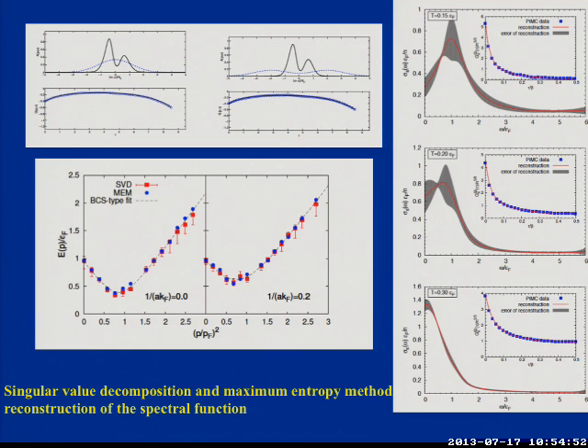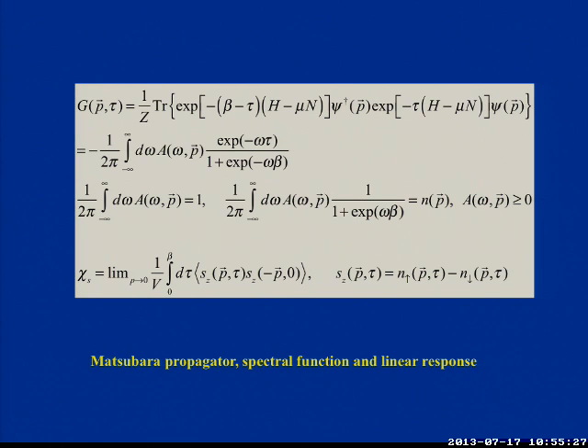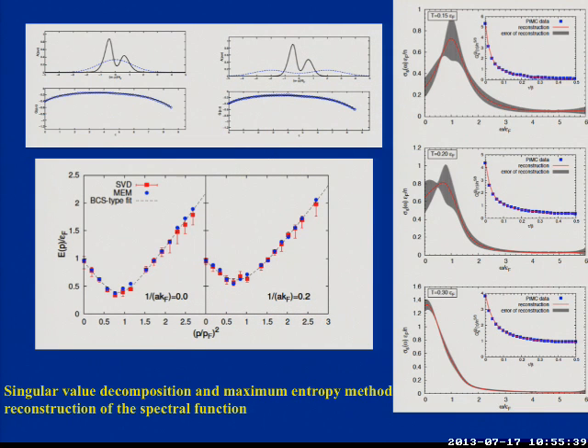Here to show you how well it works, you see here the green function, the Matsubara propagator initial and recalculated from what we determined to be the spectral function. And we do this in various ways, always come to the same result. So we have assumptions. For example, maximum entropy method, you have to have a guess. So a guess, it's 1 maximum, it's 2 bumps. Nevertheless, when we minimize, we obtain that result. We have error bars, because obviously this problem is ill posed, because we have less information here than is in there. So when you invert, obviously, you don't have all the information. So if you want to think in terms of Fourier modes, you don't have all of them. This is the error bar due to that. Okay, so this is the spectral function. I think this, no, this is not spectral. This is conductivity in this particular case, but this is the error bar.